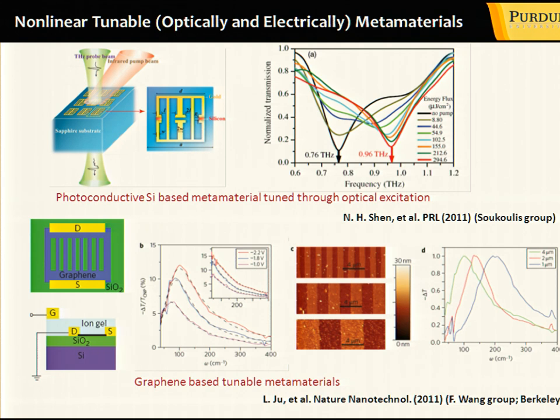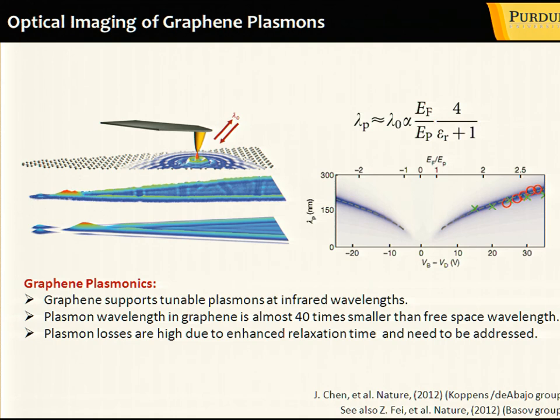As I said, you could do both electronic and photonic circuitry on the same platform. So in this case, you have these ribbons of graphene, and by applying a voltage, you change the carrier concentration, and by doing so, you shift the plasmon resonance because it's proportional to the charge carrier concentration. That effect occurs, of course, only for polarization perpendicular to the ribbon; when you polarize along the ribbon, there is no such effect. Of course, you could obtain a similar effect by simply changing the width of these graphene ribbons.